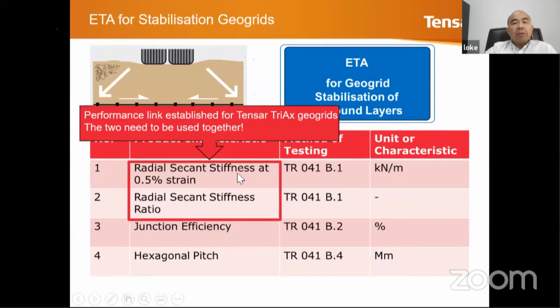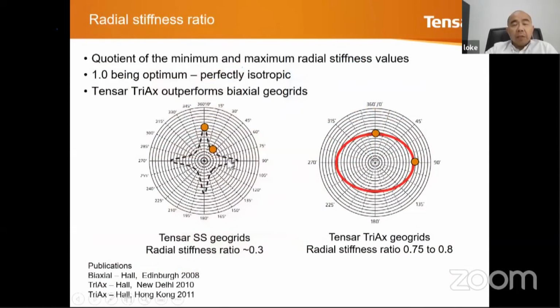All right, radial stiffness at very low strain. This is 0.5% strain, and this is very important because road pavement will start to crack if you have more than 3% strain, and therefore we want to restrict the strain as small as possible, down to 0.5%. And we need to relate those stiffness by the radial stiffness ratio. So why is this so important? Let's go back to this graph again. If you look at the square geogrids, the stiffness ratio is very low because in a diagonal direction, the stiffness is very low. Therefore, you produce a low stiffness. But with the multi-direction geogrid, you produce a very high stiffness in different directions, and therefore the stiffness ratio continues to be maintained at a very high level.